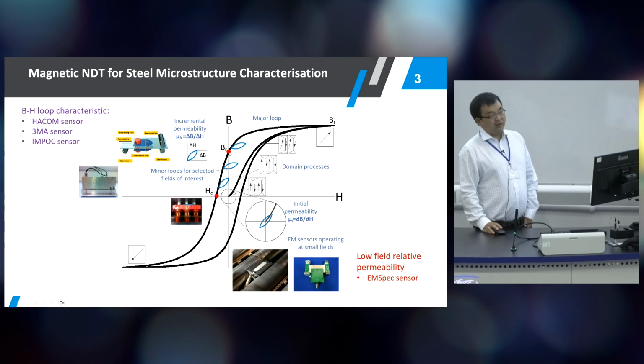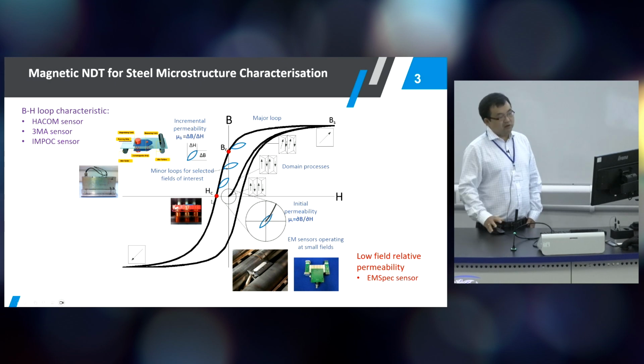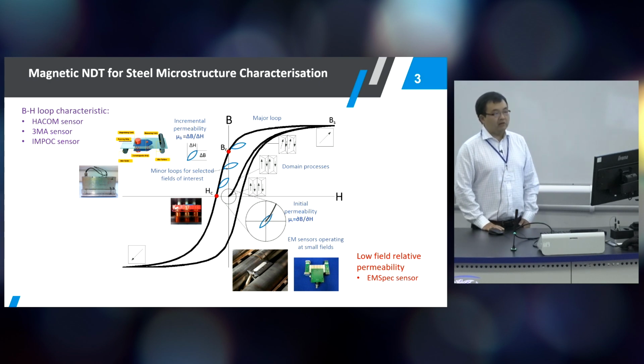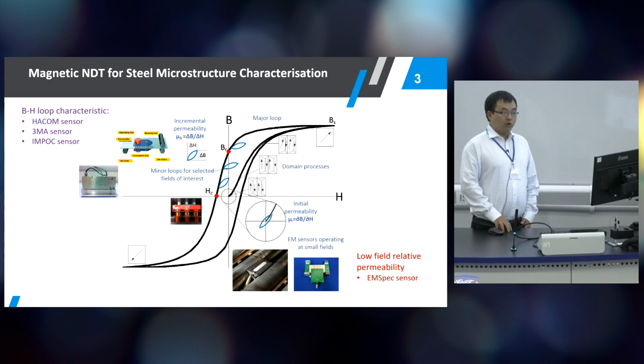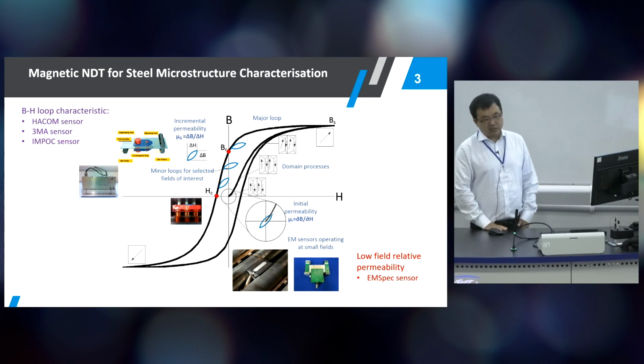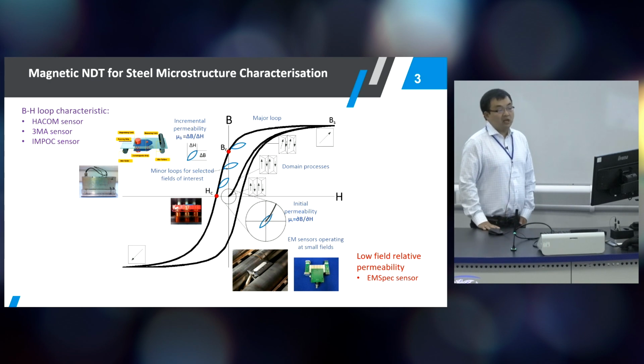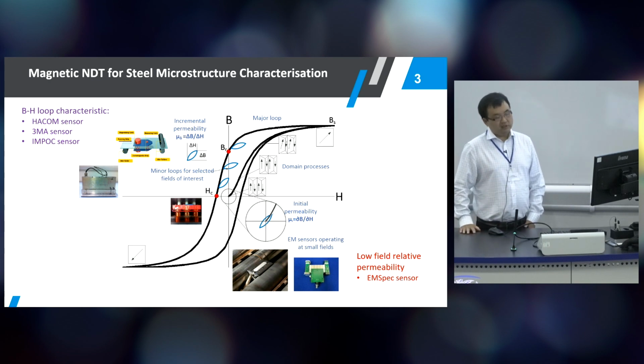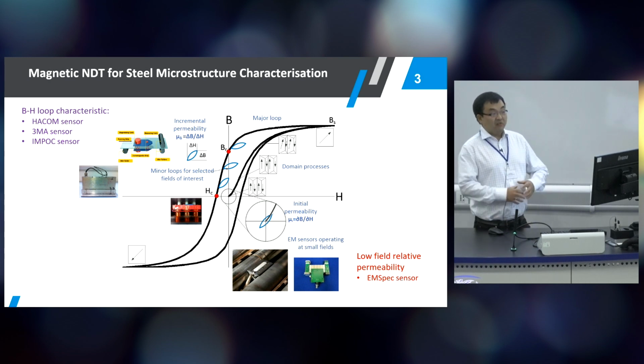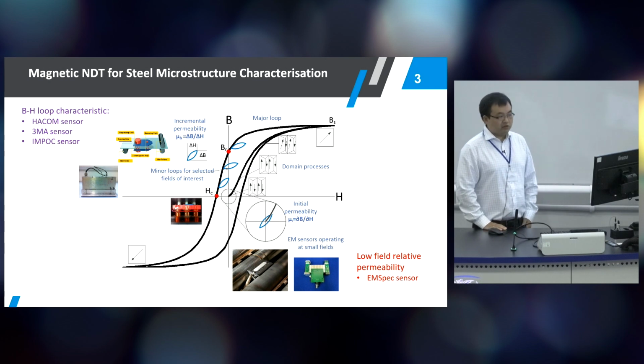And in order to get back to zero field in the steel, we have to apply a reverse field to cancel that. So what I'm trying to show here is that when you apply this magnetization process to a piece of steel, it undergoes quite various processes of domain wall movement and domain arrangement. And if you record how the B and H, the magnetic properties, change during this magnetization process, you can then infer the microstructure of the steel. So there are different techniques that apply different field strengths to look at steel microstructures.